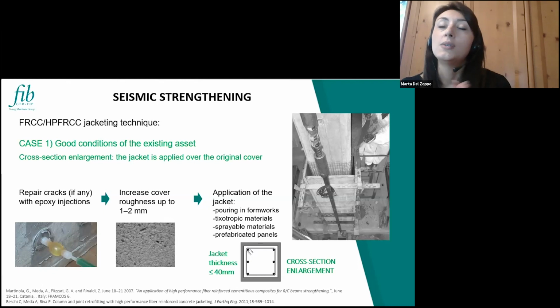So we need to sandblast the surface or increase the roughness with hammer jacks or other methods, and then we can apply our jacket with different kinds of materials. It can be thixotropic, sprayable, also prefabricated panels. The point is that this kind of material works well when applied in very thin layers. So basically, this jacket can have a limited thickness, usually less than 40 millimeters.